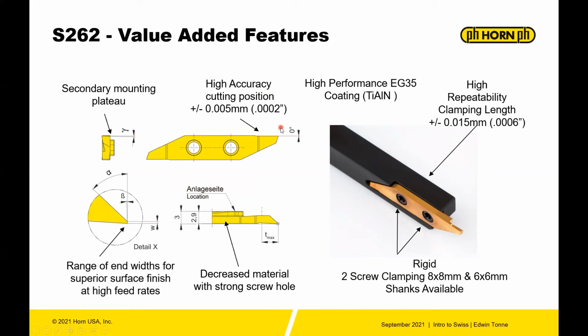You have high accuracy cutting. So this is along the lines of the SF, plus or minus 2/10 on the cutting height. You have a range of standard widths. So depending on the surface finish requirement, in a small wider groove, you can meet that. EG35 coating, which was one of our newer coating systems. The titanium aluminum nitride is the top layer. So you have a TiN layer on top of titanium aluminum nitride. Very, very effective coating system.